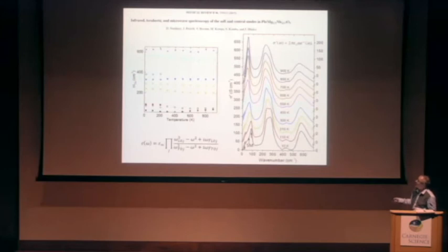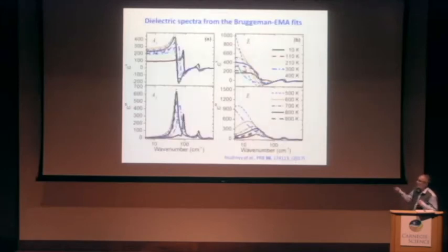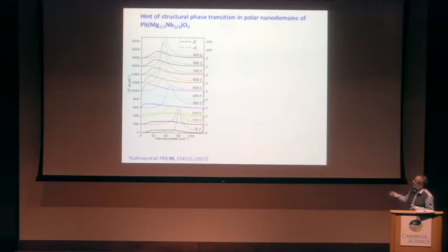splitting, and in this way we were able to calculate permittivity along the polarization, which has A1 symmetry, and the phonons of E symmetry give such permittivity. Note that here we have permittivity up to 1,000, and in this case only a few hundred. And the separated optical conductivity in both directions gives such a response.